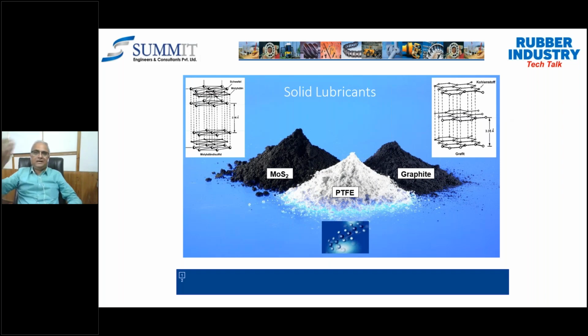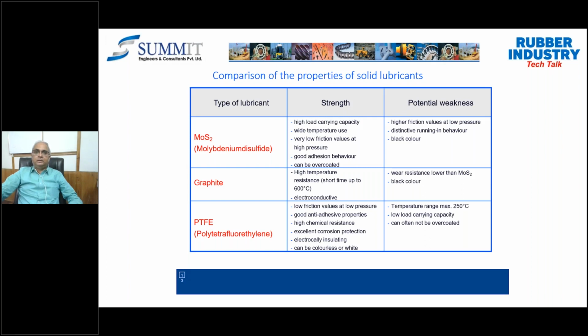Now friends, somebody would ask me a question whether I can use directly the graphite powder, or I can use the PTFE powder without any solvent and all as a dry film lubricant, because sometimes this is also essential actually. But in order to get it to adhere to the surface, you require to add certain additional material that is called the solvent or the water, and the additional binder also sometimes you will have to add over there, right? So depending upon the mechanical properties and the mechanical requirements, one has to decide whether you would like to utilize the molybdenum disulfide or the graphite or the PTFE.